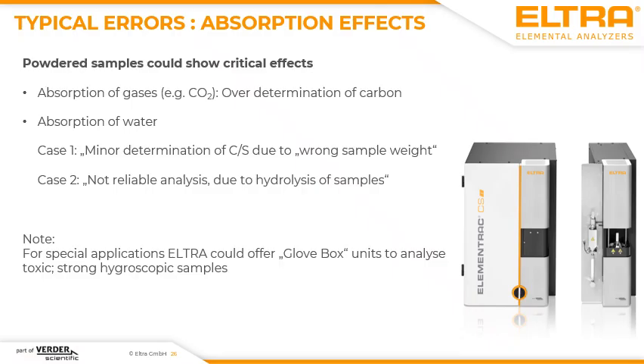Irritating results can be caused not only by heterogeneity of the sample, but also by chemical effects which take place especially in powdered samples. Powdered samples can, for example, absorb CO2 due to their high surface, and maybe they are porous inside. And one strange thing which can also happen to a powdered sample is that you have absorption of water. When you have a minor determination of carbon and sulfur, then maybe you only have, I would say, something like a moisture effect, that you have a minor determination because the sample absorbs water.